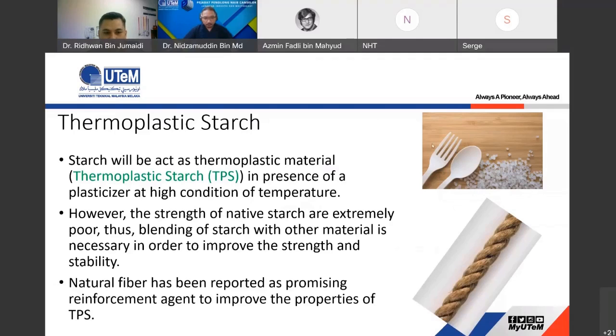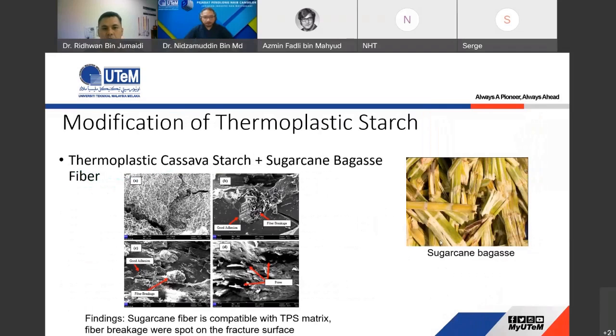However, even though TPS has good properties, being renewable and biodegradable, it has some limitations. The strength of the native starch is extremely poor. If the strength is poor, then we have to improve the properties. The blending of starch is necessary in order to improve the strength and stability of the materials. Natural fiber has been reported as a promising reinforcement agent to improve the properties of TPS. So we use natural fiber as the reinforcement for the TPS.